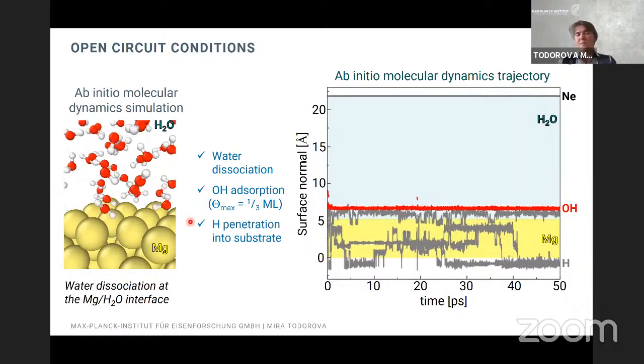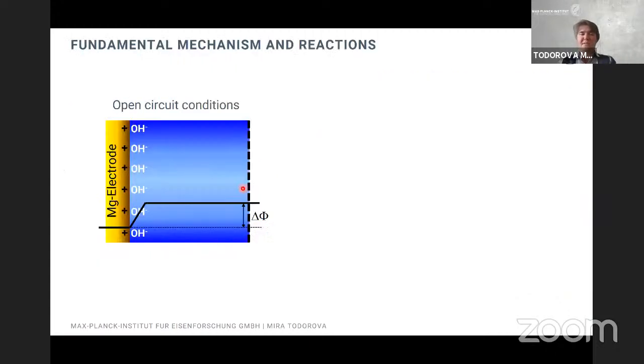We find also a maximum adsorption of a third monolayer of OH on the surface. This is consistent with these fundamental mechanisms that we discussed. Obviously, by adsorbing OH on the surface, the system is able to screen all the charge on the metal electrode. So under open circuit conditions, the maximum coverage that can be reached is one third monolayer. And this is also consistent with other studies.